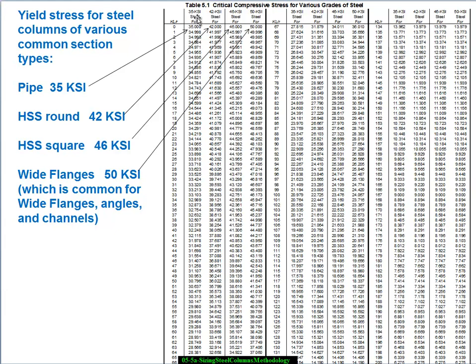Across here, I've got 35 KSI steel, 42 KSI, 46, and 50. And then I've repeated those again. So in other words, this table is dealing with four different stress grades. And they correspond to pipe. This is sort of standard plumbing pipe, which has been adapted to structural purposes. Its designated yield stress is 35 kips per square inch. HSS round, which has a yield stress of 42 KSI. When we take this round and we squash it into square, we work harden it. So actually it goes up to 46 KSI. And then we have wide flanges. And we've just included the 50 KSI because that's kind of our most common grade. And that's a common grade also for not just wide flanges, but angles and channels also.